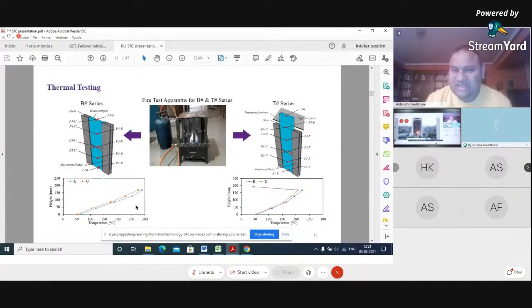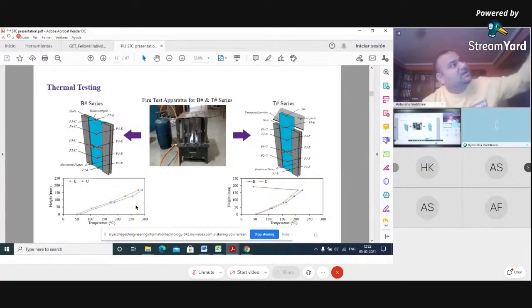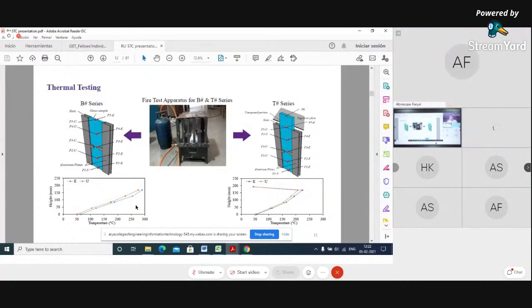So this is the basic testing that we have performed on what kind of strength glasses have once they are in a fire, and we obtained a very interesting result. You might be aware that the glass transition temperature is very high. So we tested it, communicated these results to a journal, and they are published. Glasses never fracture because of high temperature. Even at 500 to 600 degrees centigrade, glasses can withstand if they are uniformly heated. Uniformly heated means if there is a window and a fire, and the complete window has the same temperature, it may not break.